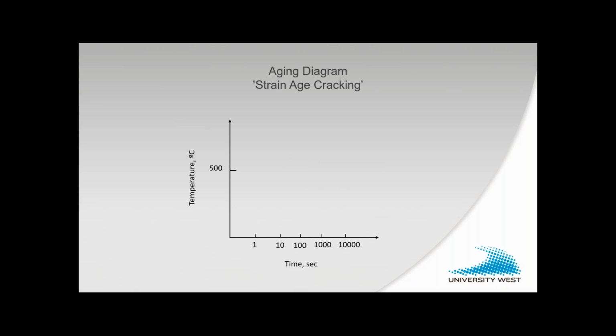Strain age cracking is highly connected to the precipitation of hardening phases in the precipitation hardening nickel-based superalloys. One could say that the standard grade alloy 718 was developed in the past because the industry suffered severely from strain age cracking in Waspaloy and other alloys, and demanded a new alloy which had less propensity towards strain age cracking. So alloy 718 is more or less immune to strain age cracking, but that is because it's primarily strengthened by gamma double prime and not gamma prime. Gamma prime is a precipitation hardening phase that precipitates very fast in the material, whereas gamma double prime takes much longer time in comparison.